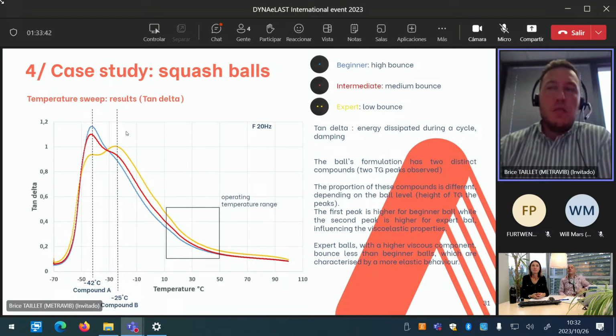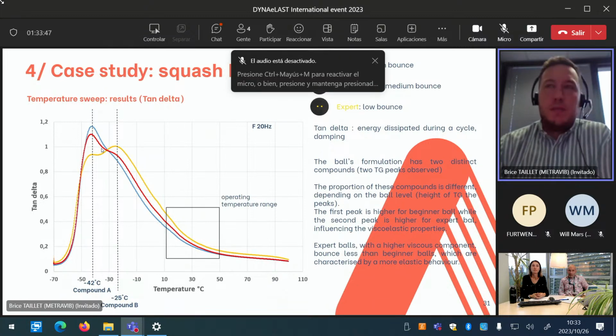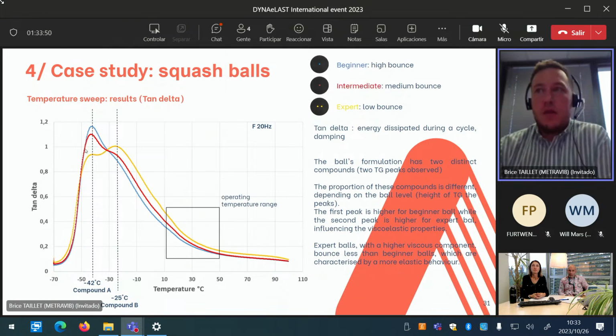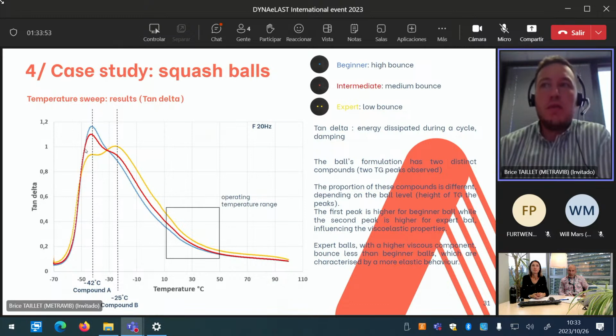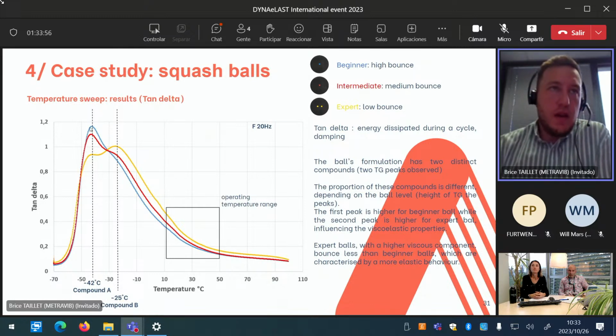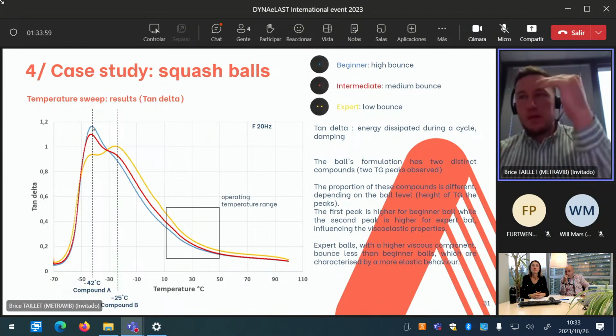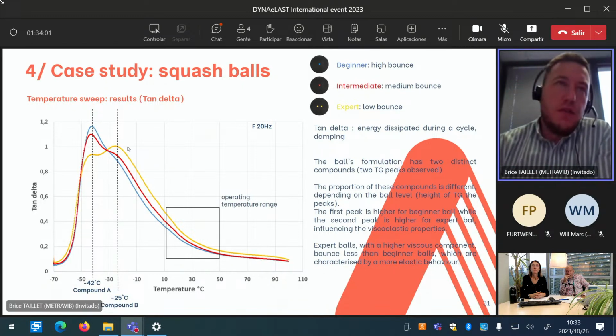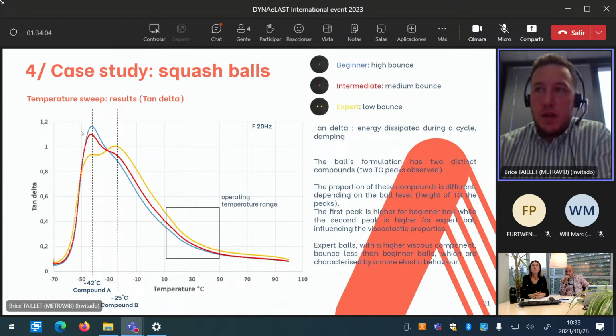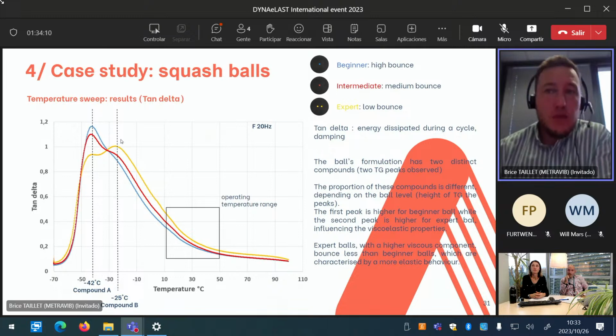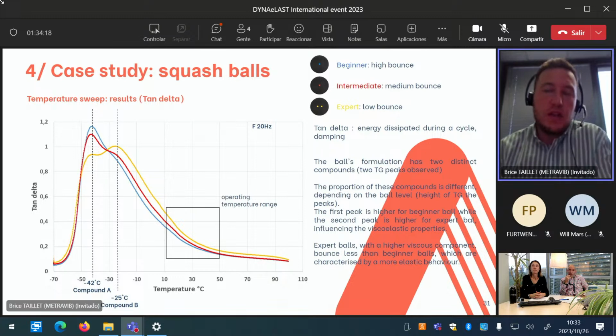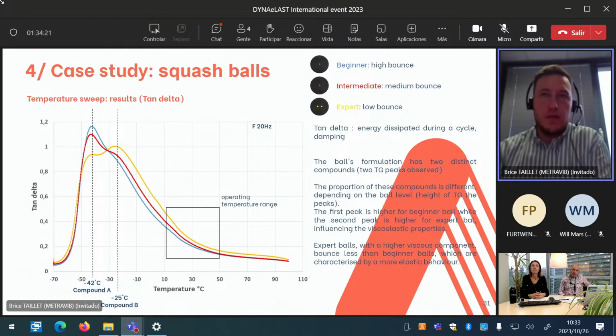We can see that the ball formulations have two distinct compounds because we observe 2 Tg peaks, okay? And the proportion of these compounds is quite different depending on the ball's level. For this, we have to look at the magnitude of the Tg peaks. The first peak is higher for the beginner ball, while the second peak is really higher for the expert ball, influencing the viscoelastic properties. So expert balls with a higher viscous component bounce less than beginner balls, which are characterized by more elastic behavior. It's quite obvious.